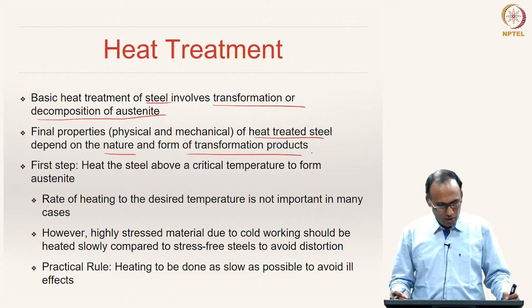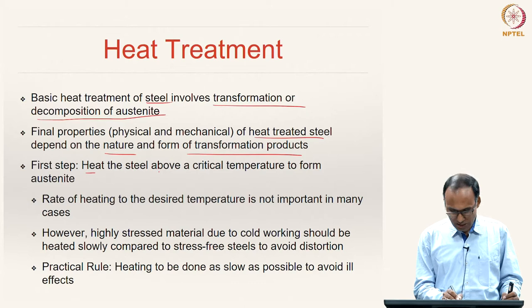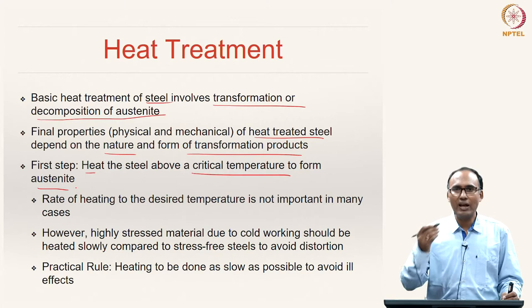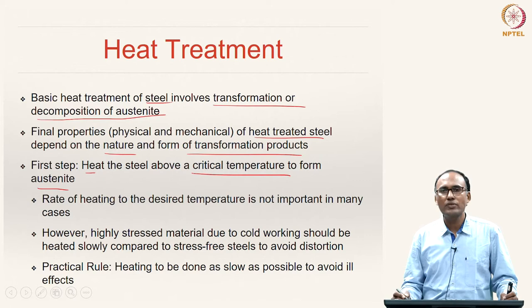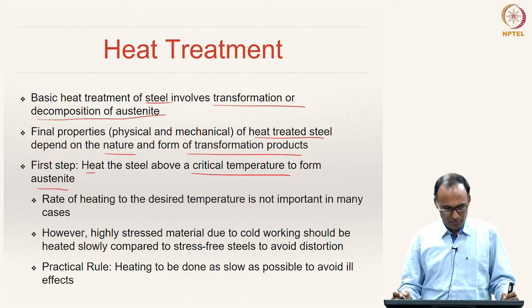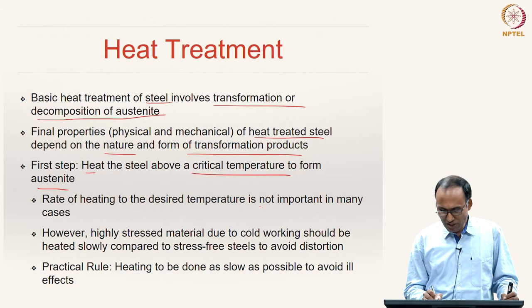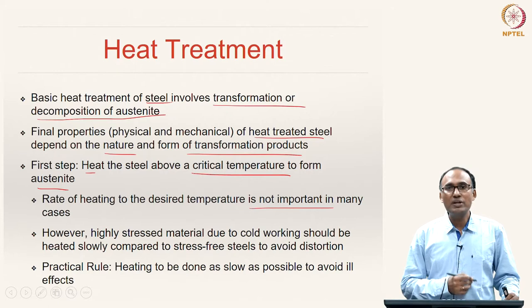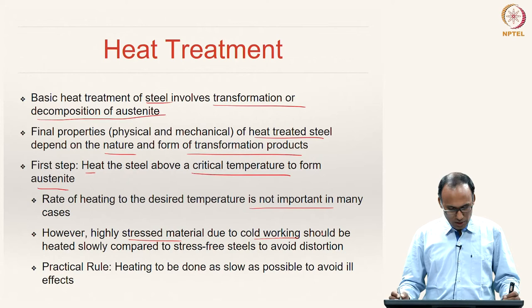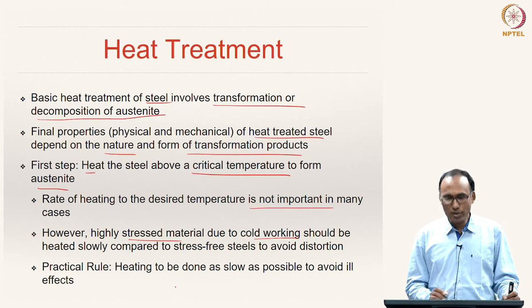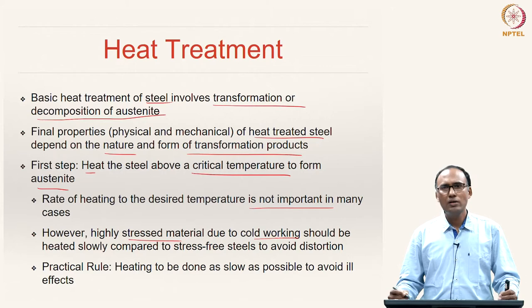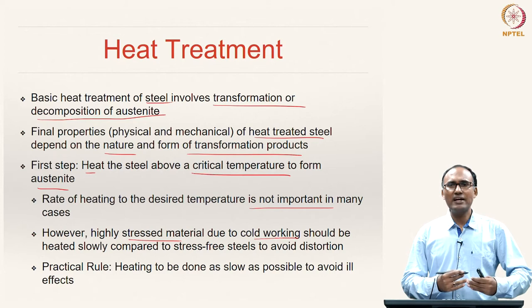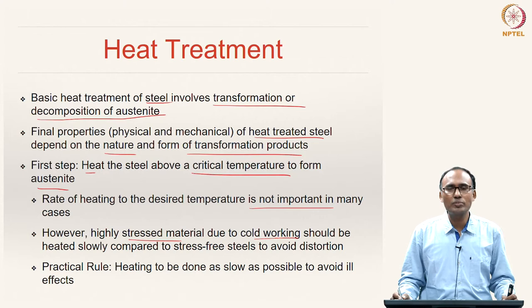The first step in the heat treatment process is to heat the steel above a critical temperature to form austenite. Depending upon the alloy composition, you need to heat it to a certain temperature above which austenite is stable, where the entire microstructure is completely transformed to austenite. The rate of heating to the desired temperature is not an important criterion, but if the material is already pre-stressed due to cold working, we want to heat it at a comparatively slow rate to avoid distortion. The heating rate is not as stringent a condition as the cooling rate.